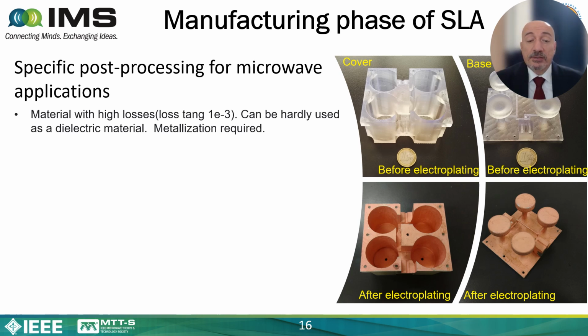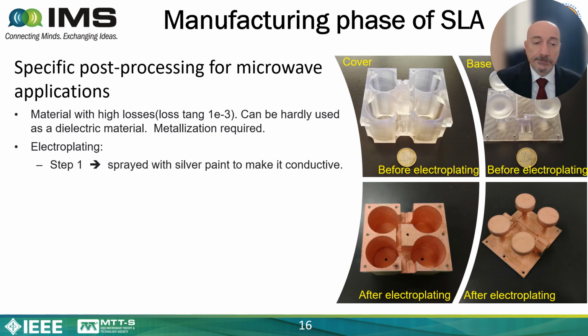Instead of using it as the dielectric material, we use this just as a support for the metallization in order to shape the metal. And indeed, our filter is considered in metal. So this means that we need to metallize the surface of this plastic. And to do that, we use the electroplating. The electroplating consists in two steps, at least as we implemented. In step one, we sprayed the surface with silver paint in order to make the surface conductive, because otherwise the electroplating doesn't work. But after the surface is conductive, you can electroplate it.